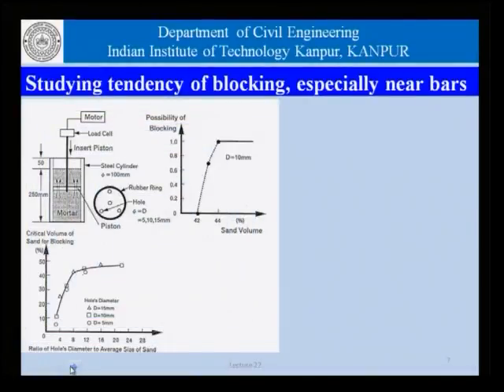Building on that argument, we had discussed this slide, which talks about the possibility of blocking and the critical volume of sand required for blocking if we were doing an experiment as shown here, where in a small cylinder we are trying to push a piston which has a configuration like this, having holes of different diameters, and these diameters are related to the particle size that we have, and we had talked about a sudden change that is occurring here and a relatively sudden change which is occurring at around this value here.